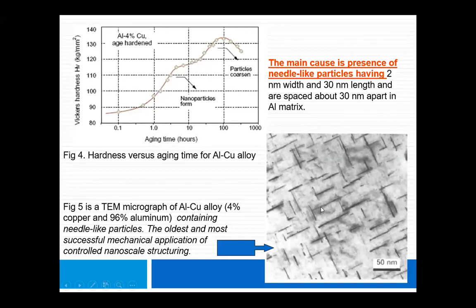You can see on the right bottom this transmission electron microscope, TEM, image. Some platelet-like structures, flaky or needle-like, are the precipitates. The diameter is maybe 5 to 10 nanometers, and the length is around 40 to 50 nanometers. The spacing between the individual needles is very important, and thickness is also important. As we have seen on the previous slide, if you are able to reduce the thickness, then instead of one, you can create many smaller needles. So the spacing between them will decrease, and the mobility of dislocations will become difficult. That is the reason hardness is increased.